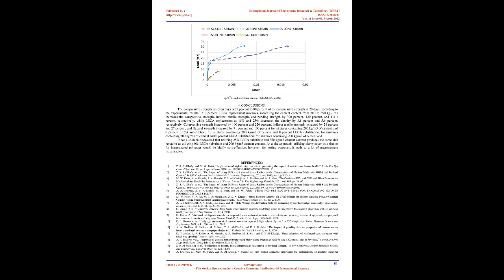From Fig. 16 and 17, it is concluded that slab S3 had less midspan deflection and ductility by 33.2% and 45%, respectively, than S2. For slabs with 350 kg per cubic meter cement content utilizing 25% LECA replacement, there was an increase in midspan deflection, reduction in stiffness, and decrease in ultimate load by 65% than 15% LECA replacement.